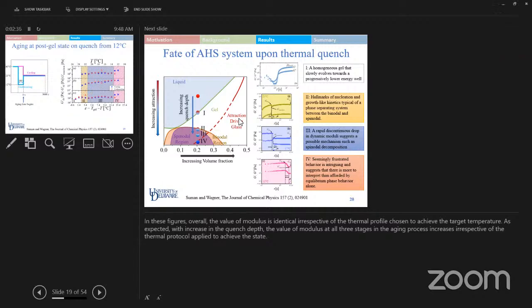From the perspective of computation, it's tough to do when it's very concentrated. Actually, 20% solid fraction is kind of a comfort zone for simulation, because you don't have many. I did, for example, hard spheres in suspension, where you have a lot of lubrication forces in between. But once the concentration goes up to 30%, 40%, it's very hard to move on with the system, because the integration time step is so stiff. You have to use a very expensive and small time step to integrate the system, so you wait a long time.